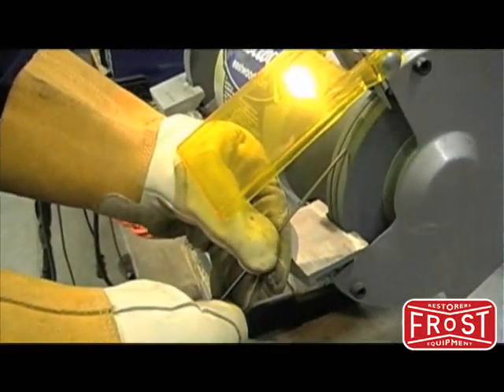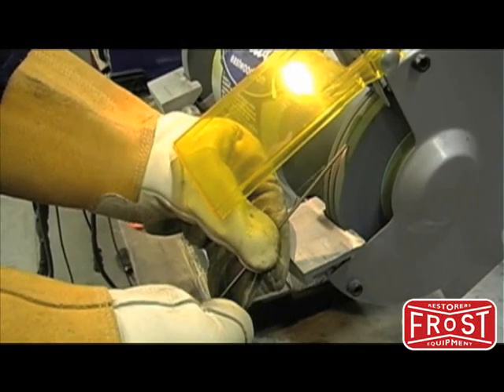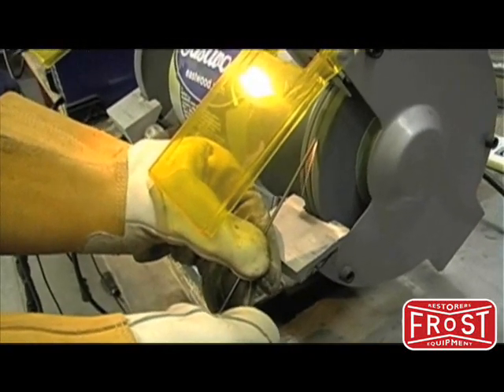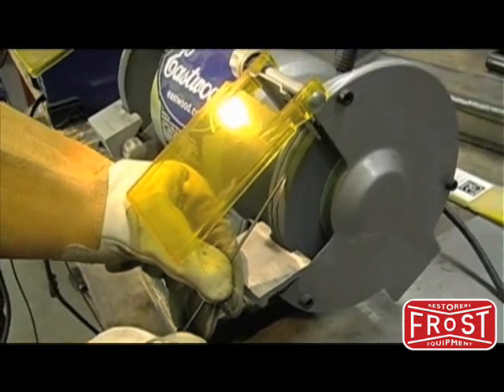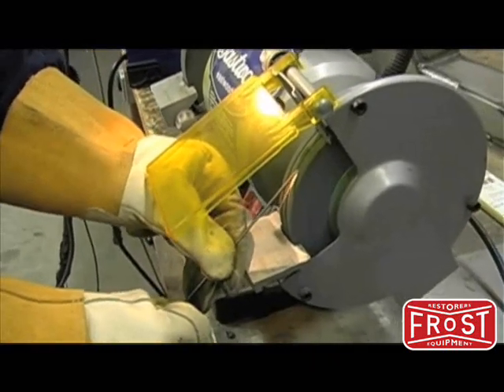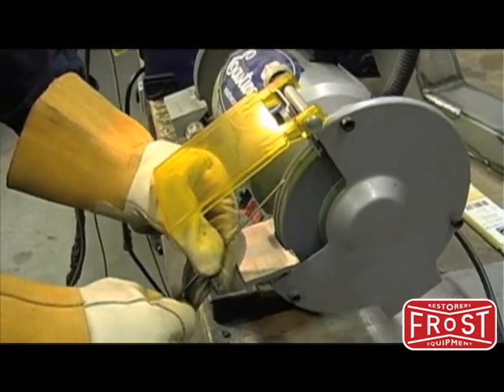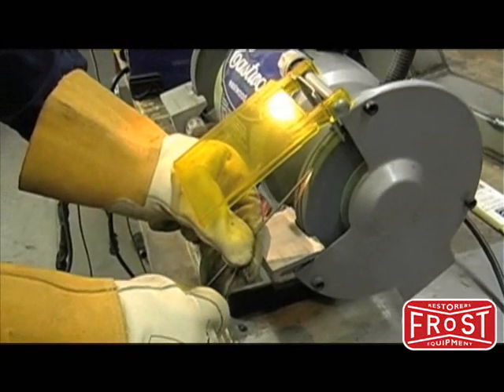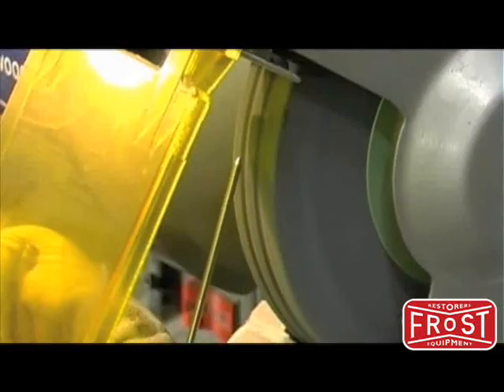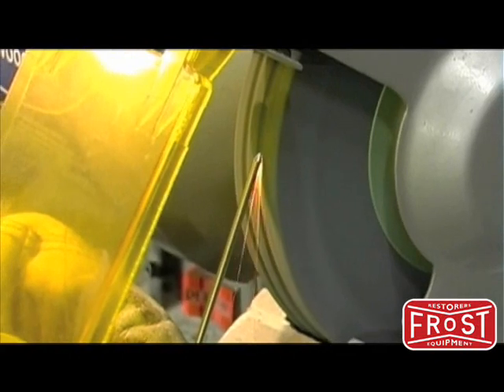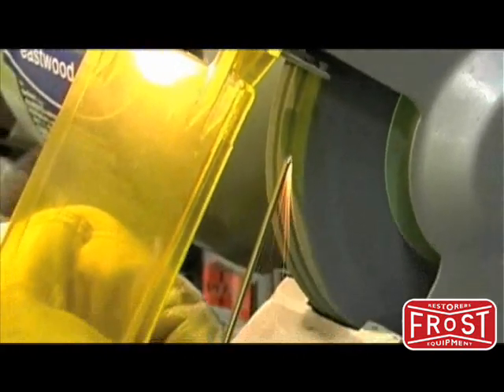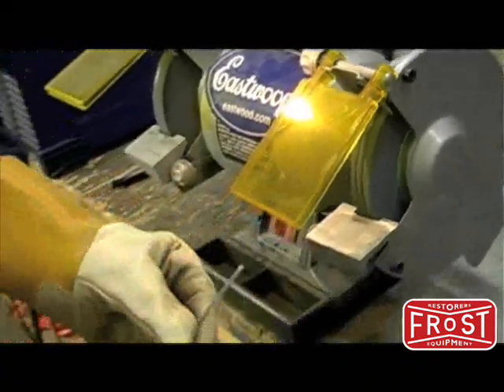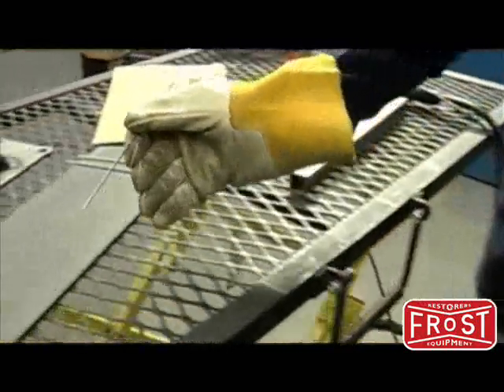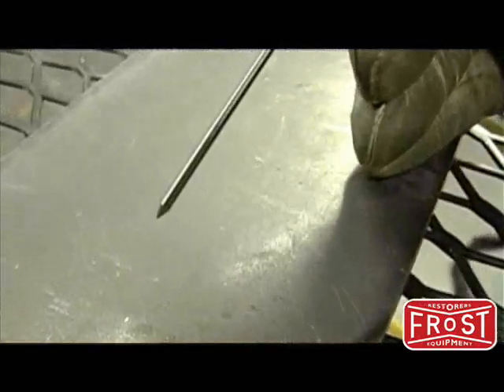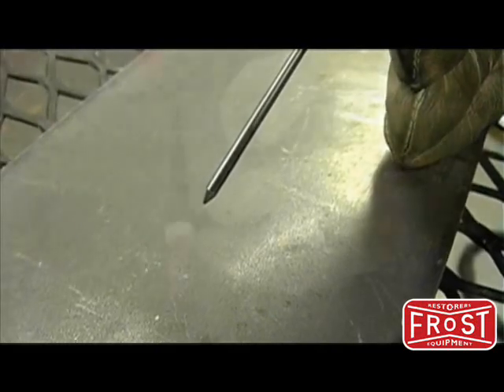It's necessary to sharpen your tungsten before using it so that the arc can be more focused on your workpiece. Always sharpen on a dedicated grinding wheel and sharpen in a parallel direction to the wheel. If you sharpen perpendicular to the wheel, you'd have problems with the arc wandering on the workpiece. The sharpened point should be around 2.5 times the diameter of the electrode.